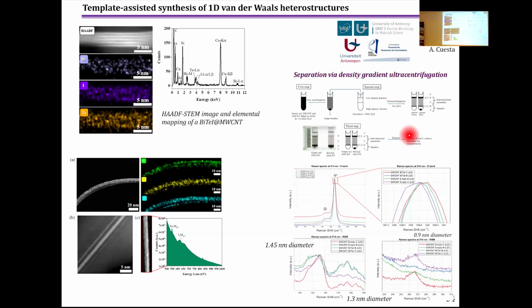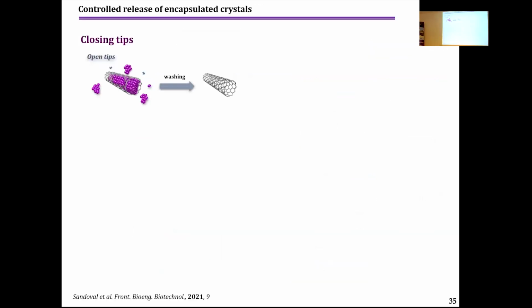The characterization also allowed the differentiation, because he observed a shift between the signal of empty tubes, the pink one, against the red one, which undergoes a shift in the Raman. So this characterization technique can also be used for discerning the presence of empty or filled tubes inside carbon nanotubes.